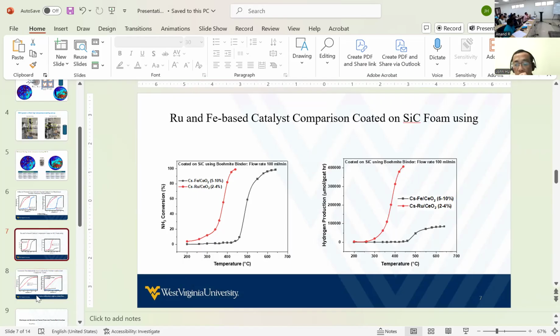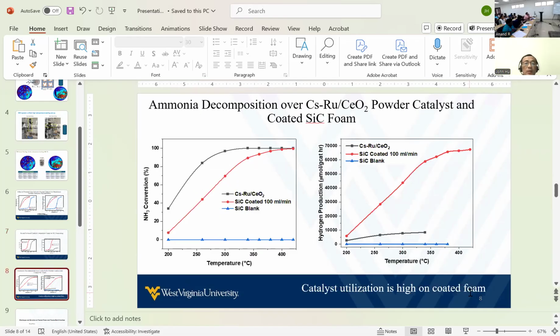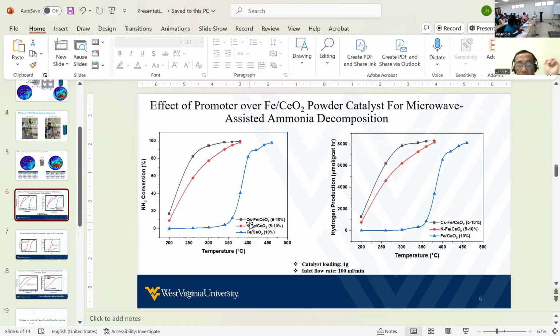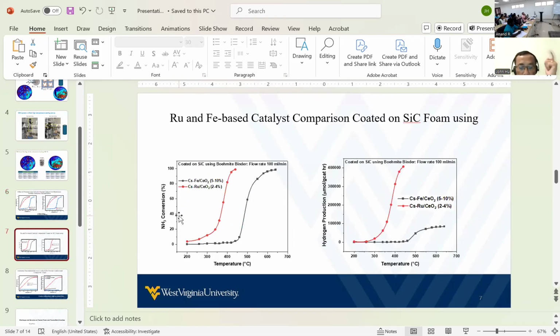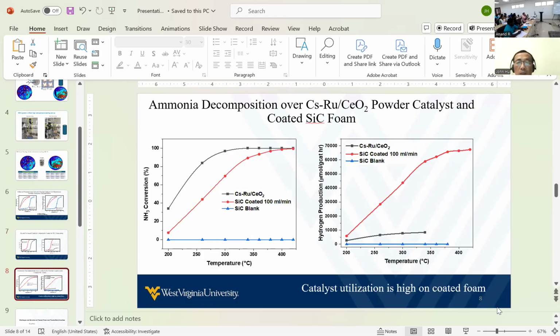So the last one. Before I end this session, I want to show you the final result. First, we know cesium ruthenium is good. Let me try to repeat. Based on this study, we know cesium as a promoter is good because we fixed the iron and changed to a different promoter. Cesium is good, but we don't know if the iron is good or not. Let's change it to another metal, which is ruthenium. Then we found out cesium ruthenium is the best. So we take this formula, cesium ruthenium, and here's the comparison.